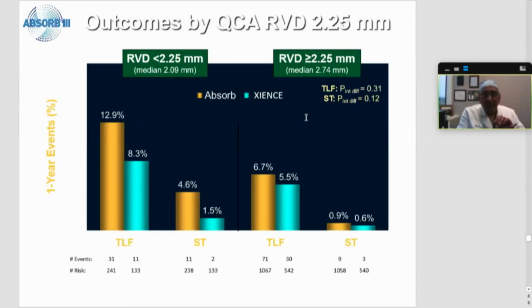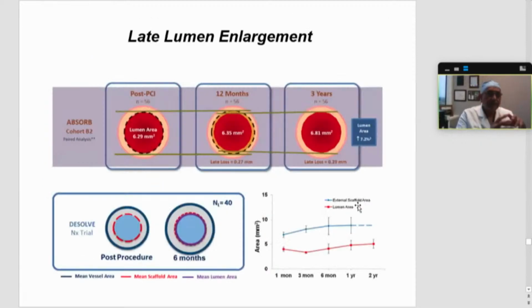However, on further analysis, we learned that most of the stent thrombosis were from small vessels. So if you put in an Absorb in a very small vessel, reference vessel diameter less than 2.25, your stent thrombosis rates were significantly higher. But if the vessel diameter was more than 2.25, actually it was very comparable and not that much more compared to a Xience. So there are certain clear theoretical advantages, such as late lumen enlargement.